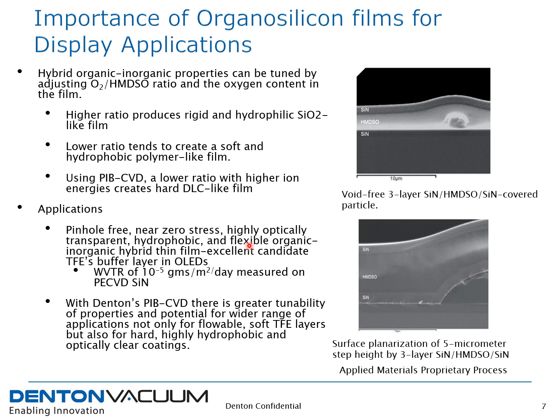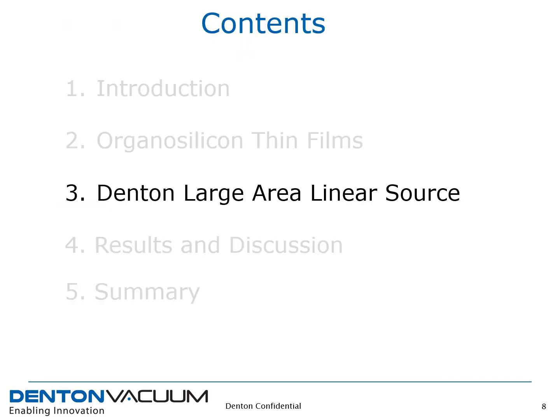Now, while these films have excellent properties for thin film encapsulation layers in OLEDs, with Denton's PIB-CVD process, there is greater tunability of properties and potential for a wide range of applications, not only for flowable, soft, thin film encapsulation layers, but also for hard, highly hydrophobic, and optically clear coatings. The core technology here is our large area linear ion source.